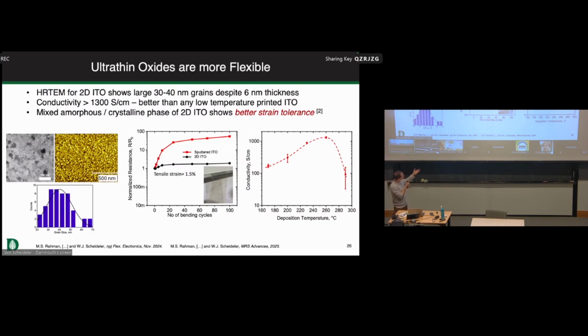The other thing that is a really interesting feature of this that we haven't really had a chance to dig into yet is that having a mixed phase, so some amorphous metal oxide that essentially separates those grains, can give you better strain tolerance. We care about strain tolerance because it is still an inorganic ceramic material, right? It's not something like a polymer that's essentially designed from the atomic scale to have greater strain tolerance, but it can be good enough essentially to sustain bending at the single millimeter scale. So something that is nearly foldable if you want to think of the mechanics of it.